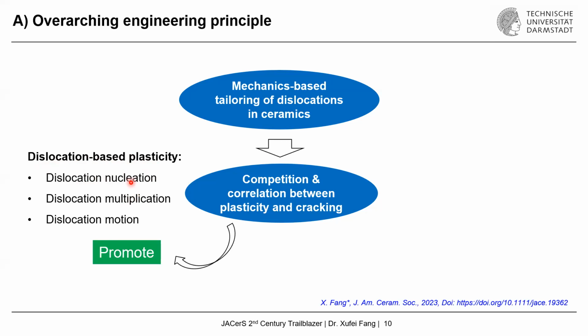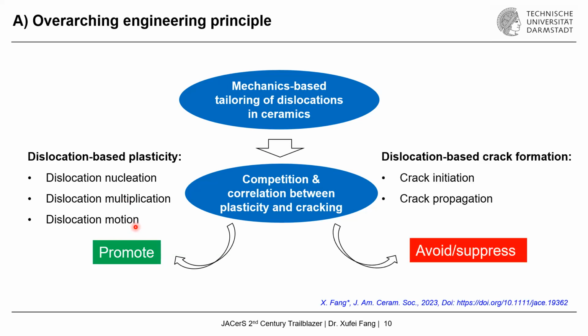So from the original dislocation-free region to have dislocations to start with. And multiplication, of course, I call it from 1 to n. So from a couple of dislocations to many more dislocations. And of course, we need to make sure that the dislocations we generate are able to move. Otherwise, they will just become pinned and pile up, and that would eventually lead to the so-called dislocation-based crack initiation and further crack propagation, which we need to try to suppress or avoid. And due to the time, I will focus mainly in this talk on dislocation-based plasticity, and for the crack-related studies, I would refer you to this paper.